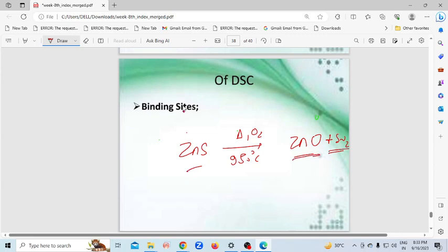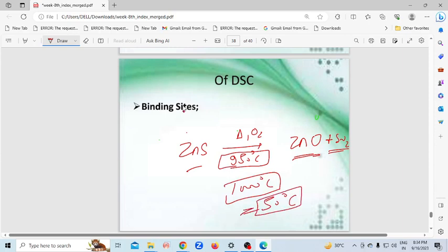So if you want to find out at which temperature this reaction will occur and how much enthalpy it requires to complete this reaction, for this purpose we use DSC for this type of sample. According to that we develop an optimized process where we need minimum energy and can fulfill our purpose. Suppose this conversion needs 950 degrees centigrade; I could do this reaction at 1000 degrees centigrade also, but then I am losing 50 degrees centigrade, wasting energy. So this type of optimization can be done by calculating the enthalpy of reactions of different processes.